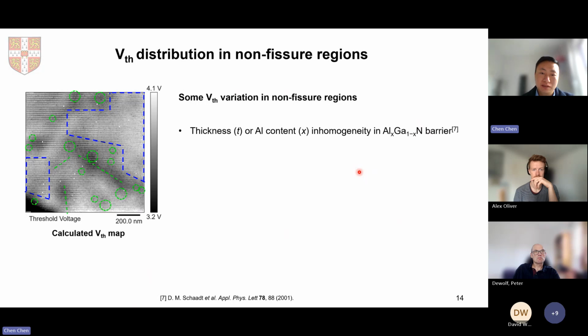For this threshold voltage variation, a potential reason could be thickness or aluminum content inhomogeneity in the AlGaN barrier layer. Again, I'm going to pick two examples: non-fissure region N1 and non-fissure region N2. I collected their threshold voltage values, and the difference is roughly about 0.2 volts.